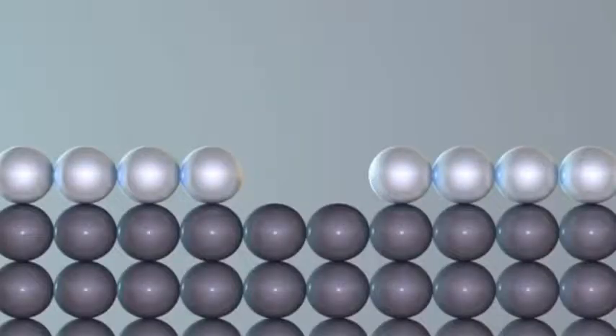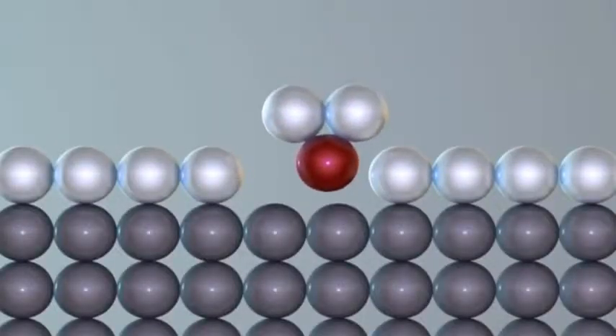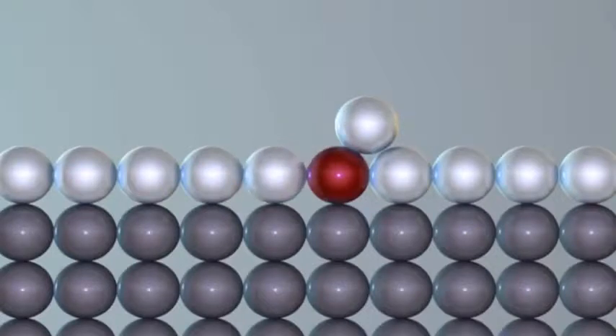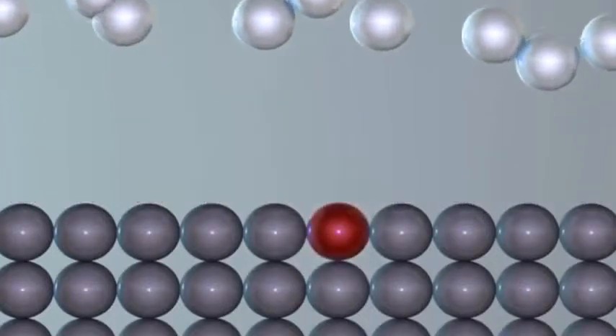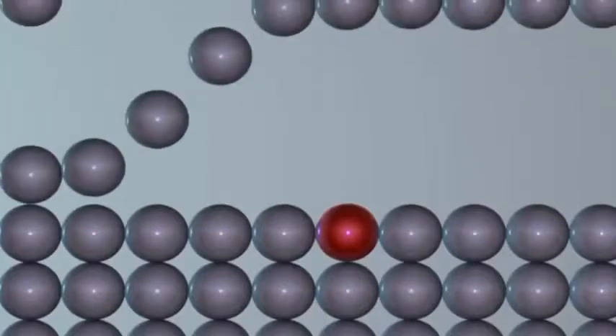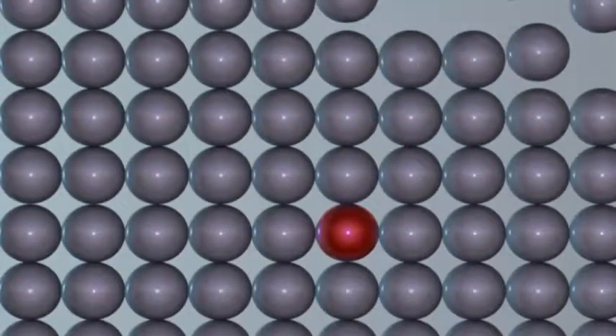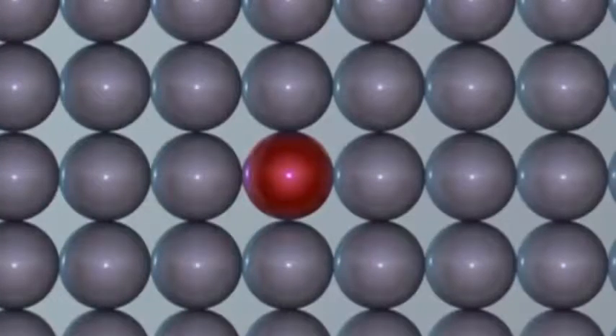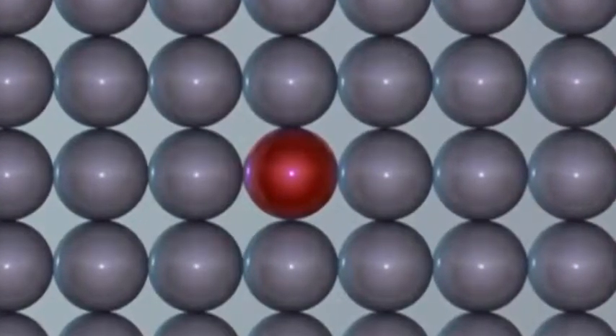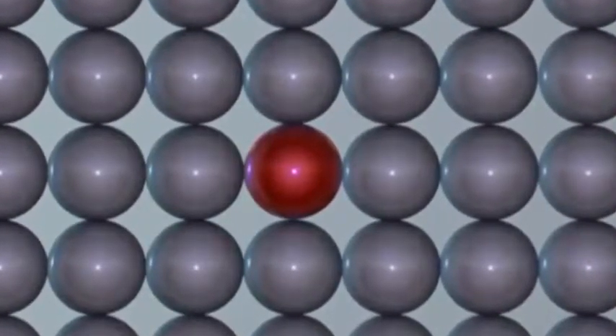And that's very reactive. And to that reactive dangling bond, we bring in phosphine gas, which will only stick to that dangling bond and nowhere else on the surface. And it's in such a way that we can bring that phosphorus and put it exactly in the one atomic lattice spacing of where we want it. And then once we've done that, we encapsulate with silicon over the top of it. And by encapsulating with silicon, we surround it with silicon atoms. So it's sitting one phosphorus atom, silicon all the way around it. It's a nice, clean environment for that phosphorus atom.